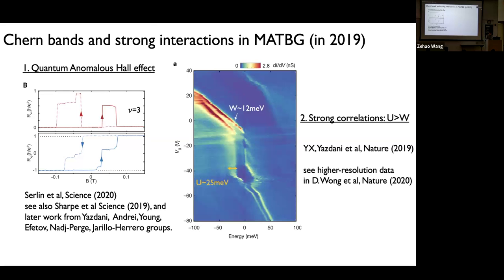And at that time, I was a PhD student doing scanning tunneling microscopy in Ali Yazdani's lab at Princeton, and we did one of the first tunneling experiments into twisted bilayer graphene, and you see these features, red lines, where the x-axis is energy and the y-axis is gate voltage. Basically, you are trying to tune those flat bands and push them to the Fermi level, and then you do spectroscopy and look at how the density of states evolves. And the bottom line here is that when the flat band is near the Fermi level, there is some anomaly that happens. For example, one of the bands will suddenly get broadened by a lot, and that actually provides us a measure of the energy scale.